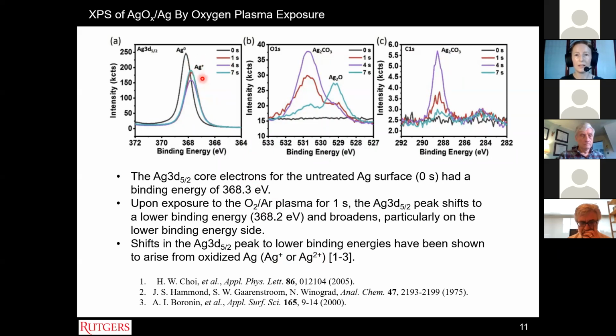So that would be the formation of the Ag2O oxide, and also potentially carbonates. By analyzing the O1s and the C1s, we were seeing the presence of silver carbonate forming for 1 second and 4 seconds, but that reduced over time, probably because there's some residual contamination or carbon on the surface during the plasma exposure.